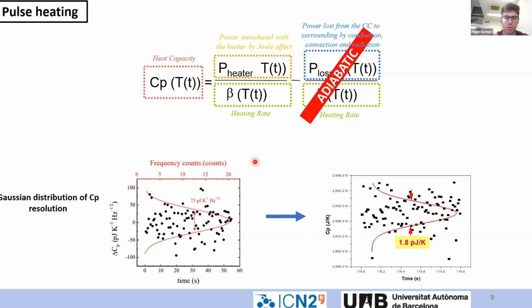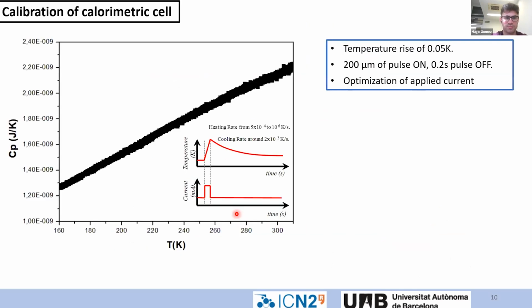We made some improvements in this technique in the past year. I'm plotting here the resolution of this technique. Before starting this project, it had a resolution of around 75 picojoule per Kelvin. Now, with the improvement in this technique and in the device, we have 1.8 picojoule per Kelvin. This is, of course, taking into account the spatial resolution of our different chips.